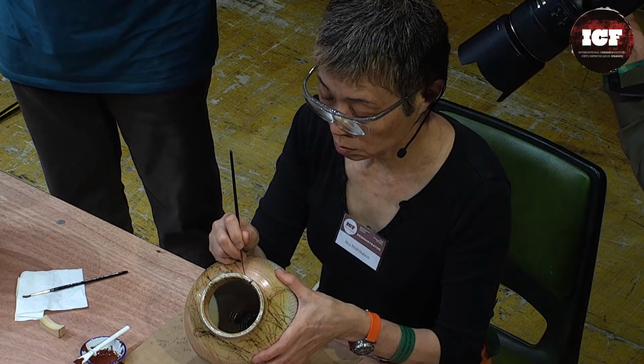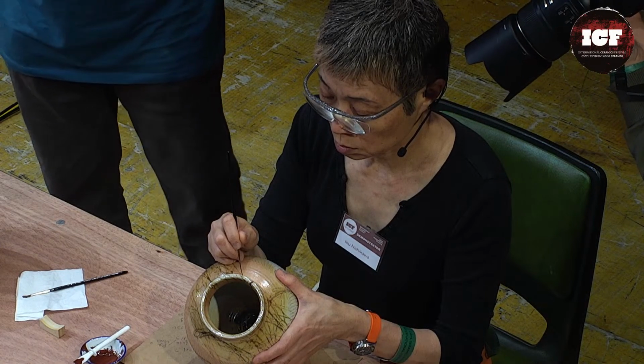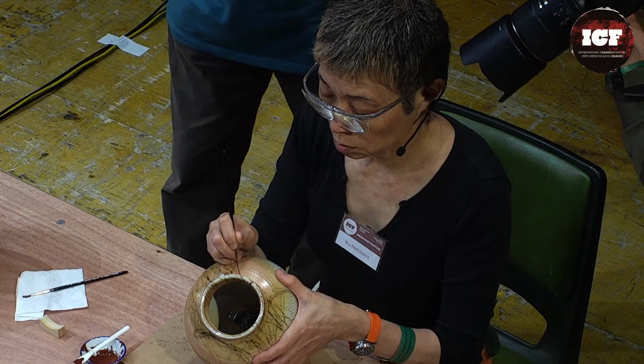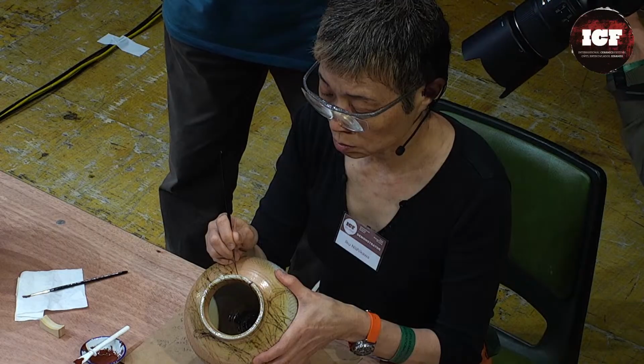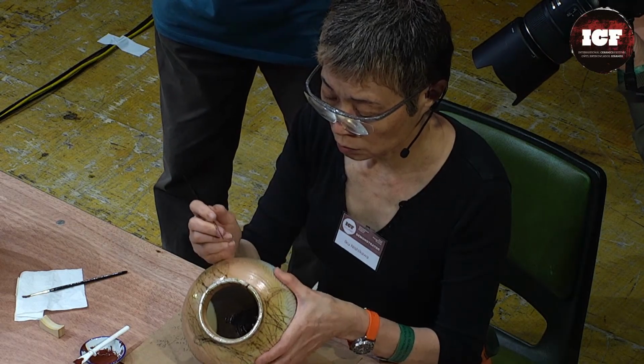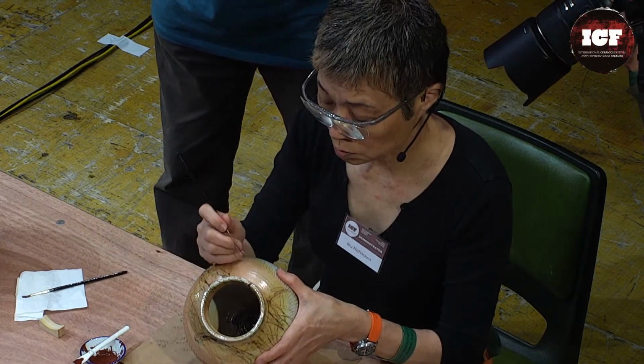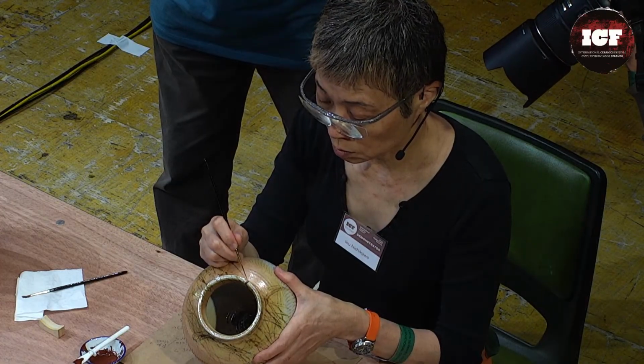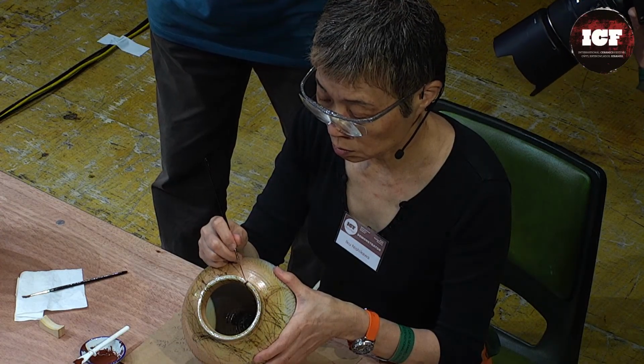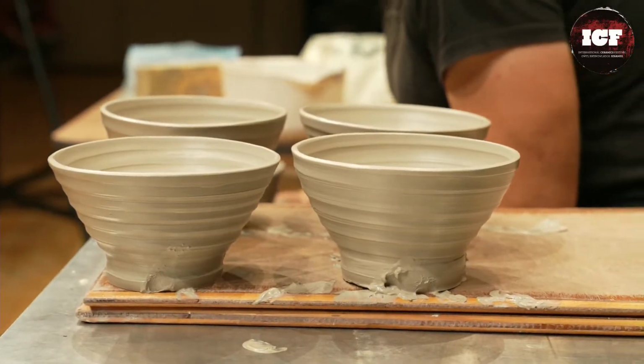So a very heavy reduction between 1090 and 1130, and a reduced cooling on a clay which has very little iron. Iron will resist the sodium. Very little iron, high alumina, and low silica.